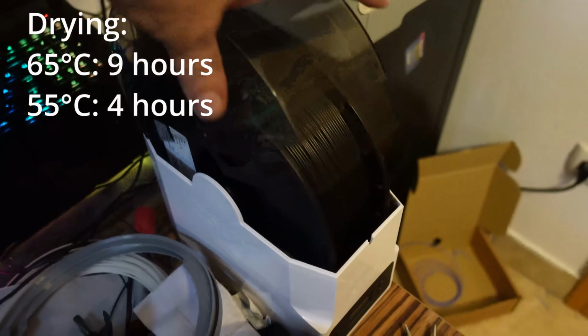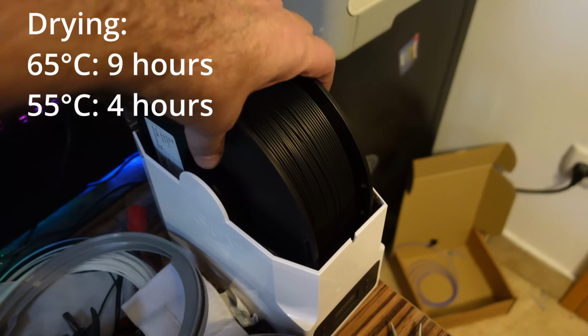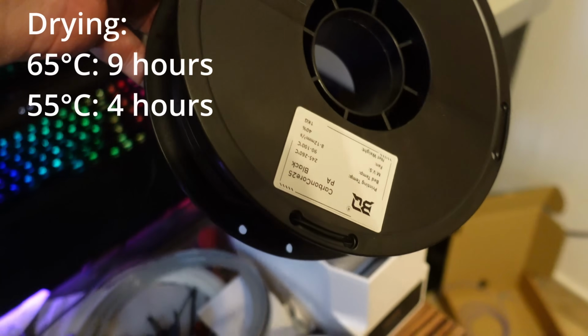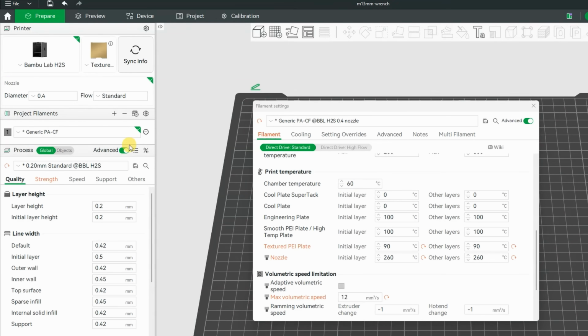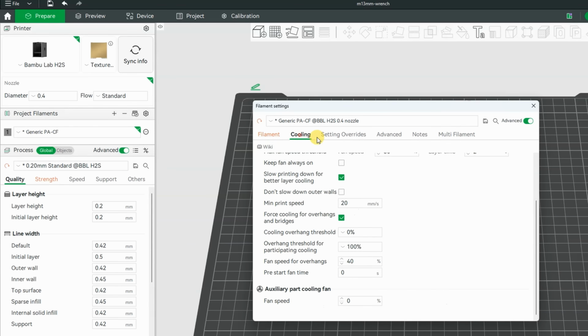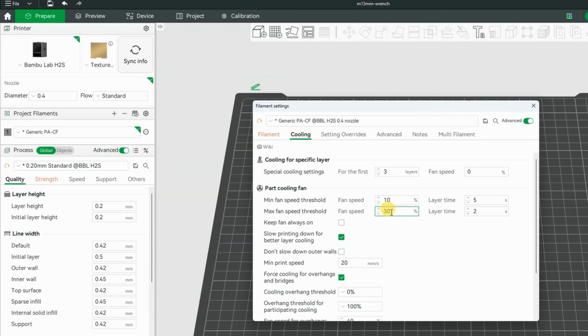And now nylon. It was in a separate dryer because the AMS cannot dry during the printing. Nylon, generic PA-CF is the salt profile: 60 chamber temperature, 90 on the bed, 12 maximal flow, and the nozzle temperature reduced to 260 because this is the maximum recommended for this material, and the part cooling up to 30%. Very short layer printing time, maybe this will be a mistake.